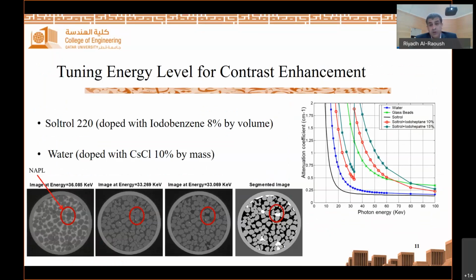One of the advantages of synchrotron tomography is that the energy can be tuned to enhance the contrast of the phases of the image for a better segmentation of the phases. To utilize this advantage, fluids used in our experiments can be doped with certain chemicals, and then the systems are imaged at energies just below and just above the edge of certain elements. For instance, in our experiments, the oil was doped with iodobenzene and the water was doped with cesium chloride.